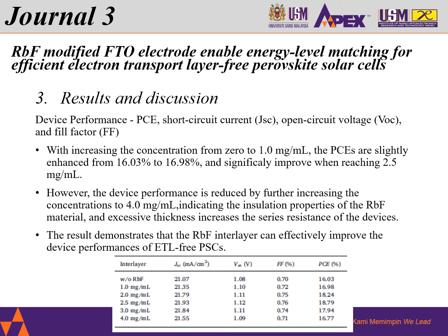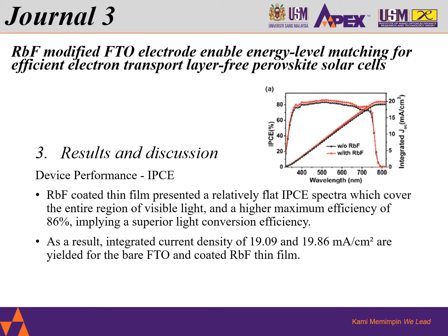Further increasing the concentration does not help to further improve the PCE, because excessive thickness of the RbF will eventually increase the resistance of the device. This result tells us that the RbF can improve the device performance. Looking into the IPCE, both the samples coated and not coated with RbF show the same or a similar spectrum, where both are relatively flat.